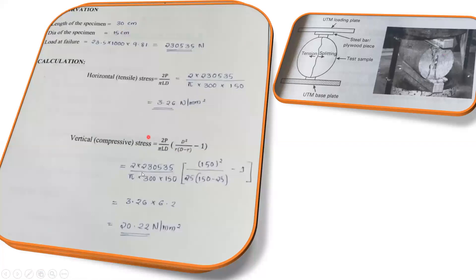For the calculation: the length of the specimen is 30 cm which is 300 mm, the diameter is 15 cm which is 150 mm, and the load at failure from the dial gauge reading is 23.5 — multiplied by 1000 and then by 9.81 to convert it into Newtons. Substituting into the formula σt = 2P / (π × L × D), the tensile strength comes out to be 3.26 N/mm².